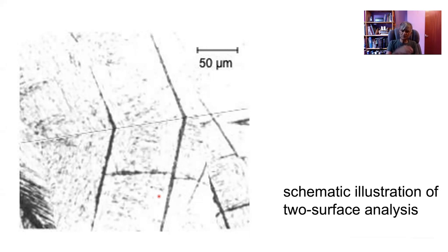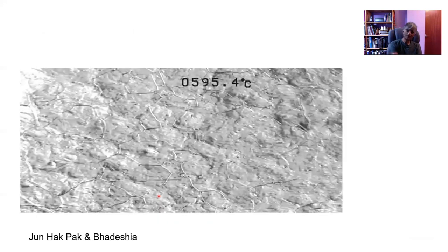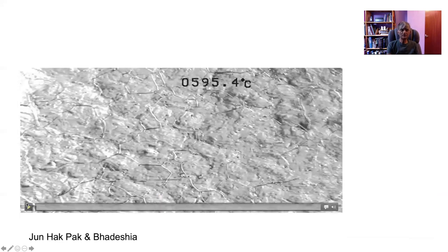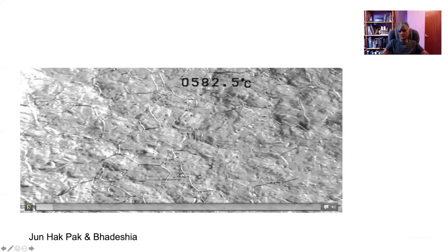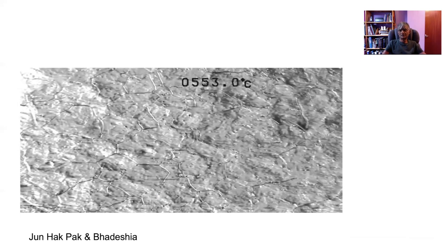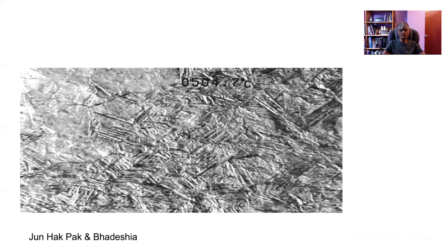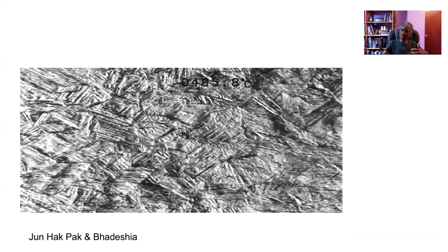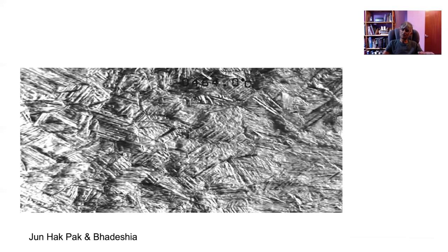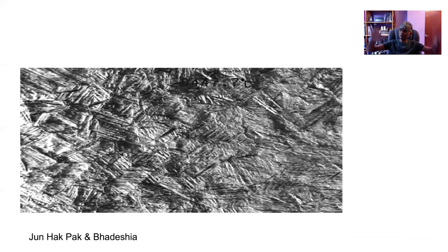Now, if we change the crystal structure by a deformation, then obviously when the bainite forms, the shape of the transformed region must change, okay? So this is a movie taken using confocal laser microscopy. And this is the temperature. And as we drop the temperature, we will get bainitic transformation. So there you go. Beautiful surface relief due to the displacements associated with the bainite transformation. If you didn't know this was bainite, this would look like an earthquake happening with mountains being created.